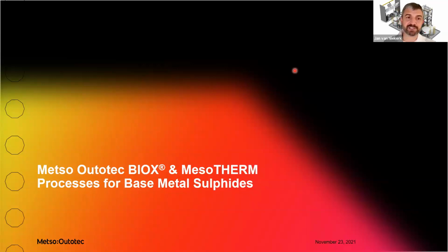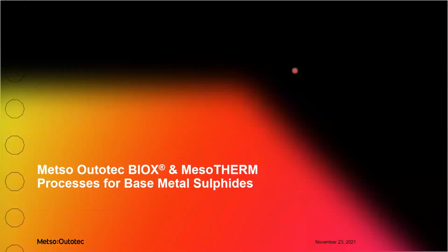However, having said that, designing a plant for sub-zero and minus 45 degree ambient temperatures does bring its own challenges as well. But certainly from a purely cooling point of view, definitely much better in the cooler climates than the warmer climates. So what are the challenges of operating at minus 40, minus 50, that range?